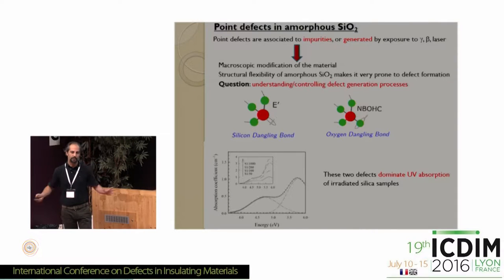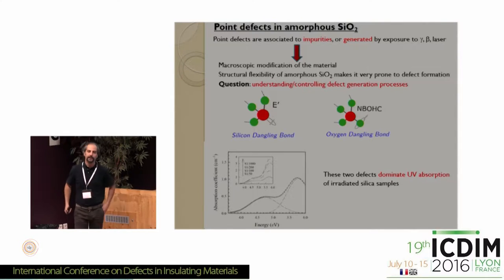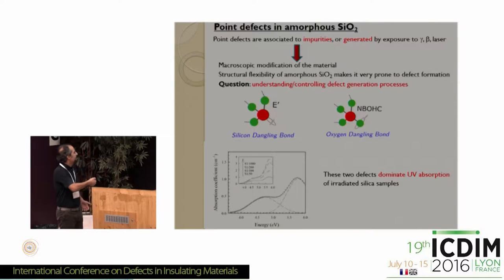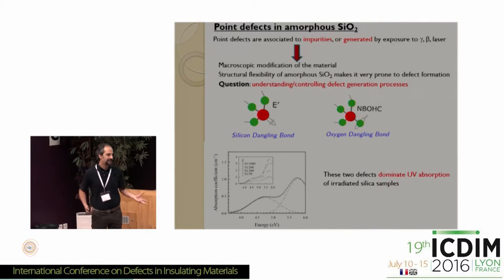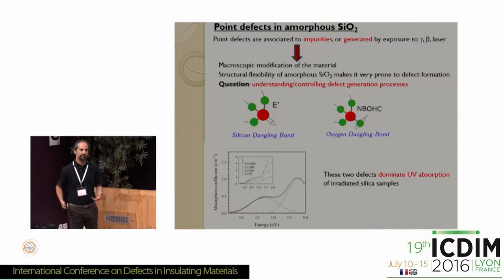These are by far the most common defects that you can find in amorphous silica. And they give rise to very intense absorption bands in the ultraviolet, in a region where the material in itself would be transparent, at 4.8 eV and 5.8 eV, respectively. So if you have these defects, they usually dominate completely the UV absorption of silica samples. So in irradiated silica samples, if defects get formed, you have a huge change in the UV absorption properties from transparency to intense absorption due to these transitions. And another thing which is useful to know is that crystalline SiO2 is less prone to the formation of defects.